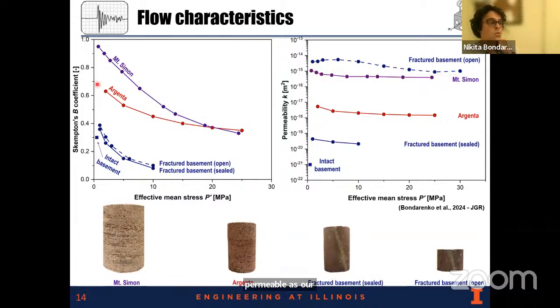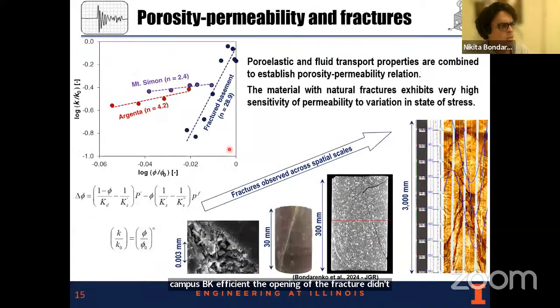In case of the open fracture, it can be as permeable as our reservoir rock. Interestingly, in terms of the undrained response, the Skempton's B coefficient, the opening of the fracture didn't affect it significantly. So we can combine these two tests together, the hydrostatic loading and fluid transport properties, to establish the porosity-permeability relationship, which shows how change in porosity will be associated with change in permeability.